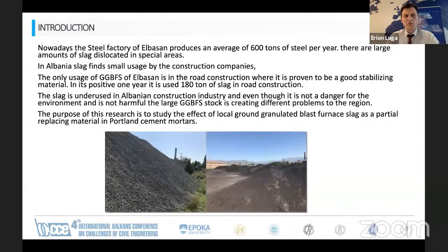Nowadays, the steel factory of Elbasan produces an average of 600 tons of steel per year. There are large amounts of slag dislocated in special areas. In the figures below, you can see some of the disposed slag inside this steel factory. The only usage of ground granulated blast furnace slag of Elbasan is in road construction, where it is proven to be a good stabilizing material. In its best year, about 180 tons of slag were used in road construction, so it's not enough. So slag is still underused in Albania.